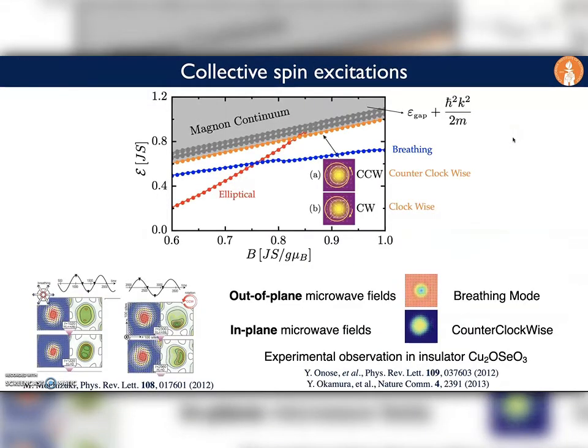The spin wave spectrum around a Skyrmion consists of the usual propagating spin waves with a quadratic dispersion above a gap, although a number of localized bound states exist below the magnon gap and correspond to Skyrmion deformations. Of particular importance for our work is this counterclockwise mode with an energy exactly at the gap, which corresponds to a rotation of the out-of-plane spin component around the Skyrmion core.